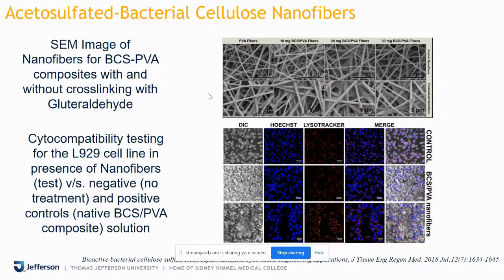So we created water soluble bacterial cellulose sulfate, and in composite with PVA, we created nanofibers, which is shown in the figure. You can see the top panel. These are the nanofibers that were created using PVA composites of bacterial cellulose sulfate. And we used electrospinning technology, where you create these solutions with various viscosities, and then you apply high voltage at the tip of the needle, where it will spray the solution and create nanofibers. These nanofibers were later used to check the cytocompatibility as well as the adherence nature of the L929 cell line, which is a mouse fibroblast cell line.